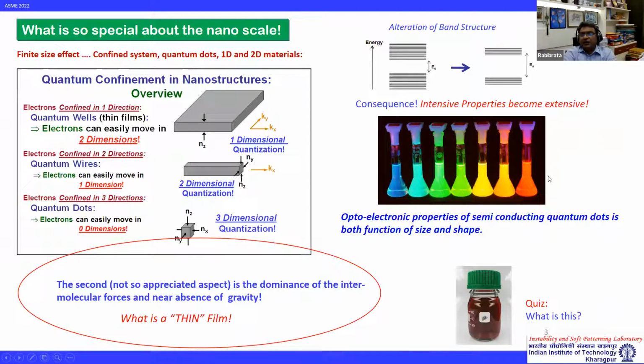And I'm sure people who have some scientific background in this particular area or materials see this type of picture very, very commonly. This is semiconducting quantum dots of different size. And if you excite them with UV light, they emit color at different length scale. So essentially what happens is, as you keep on making things very, very small, the defect states change or the band structure starts to change. And as a consequence, intensive properties, which are generally size independent, become a function of the size itself. For example, for quantum dots, their color or their emission depends both on their size and shape.